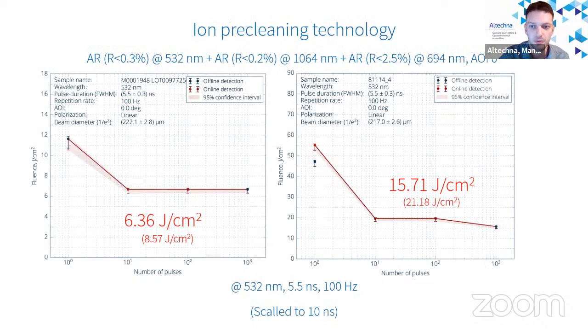The second example is a multi-wavelength AR-coated optical component. Without pre-cleaning, the typically achieved value was 8.5 joules per centimeter square. When we scale the result to 10 nanoseconds pulse duration, because tests were executed at 5.5 nanoseconds, we can rescale it to 10 nanoseconds, which is typically used in the market.